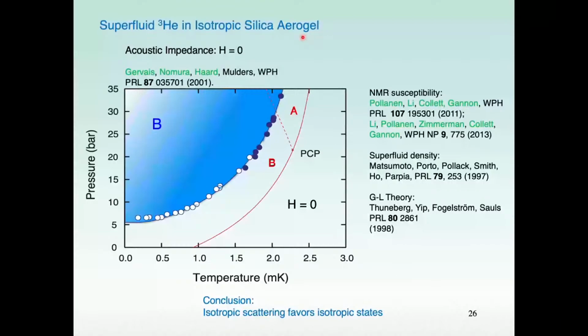Now, what about the nature, the symmetry? I've emphasized the importance of symmetry and the identification of symmetry in the superfluid phases. And well, now we have a different kind of superfluid phase, and you might ask, what kind of superfluid phase is it? And of course, you're going to see here that it's blue and it's B. Now, that comes from zero field measurements. And in my group, Guillaume Gervais and others in my group showed that this was the phase diagram. The actual delineation of what the phase diagram transition temperature is from normal to superfluid is a collaboration, if you wish, between the Northwestern and the Cornell groups in nice agreement.